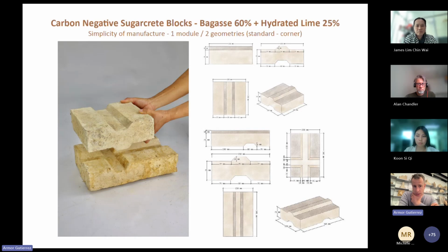We used a mix of bagasse and hydrated lime. So we put two components together, which was slightly different. So this is mineral based rather than silica based. And the idea was to create a block that would have a slightly simplified version from the interlocking blocks that we did for the slab, but still have an interlocking component into it,